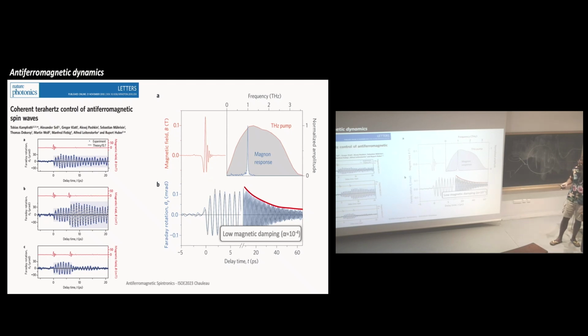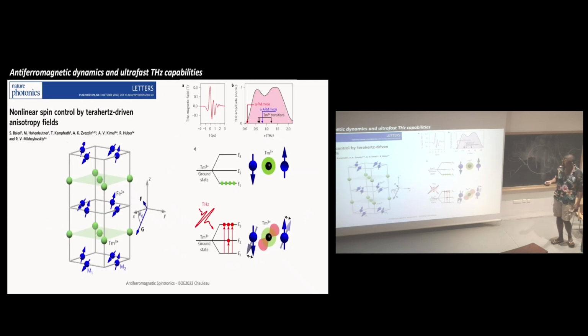But of course, as I said, magnetic field is not usually the best way to manipulate antiferromagnetic materials. So then you can use some other tricks. For this, I will illustrate with another work, which has been very nicely done. What they are using here is TmFeO3. And the nice thing is they will use a pulse of anisotropy. How do they do that? They shine another terahertz light, but this terahertz will drive some transition and change the population. And by changing this, you will change the anisotropy.